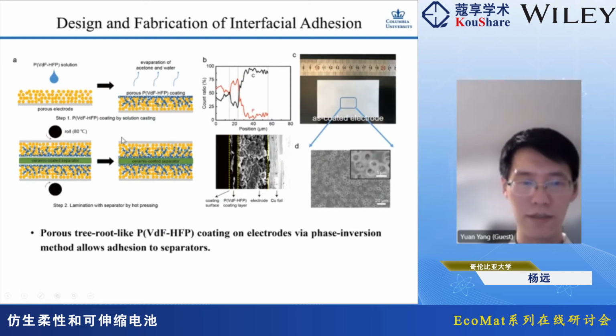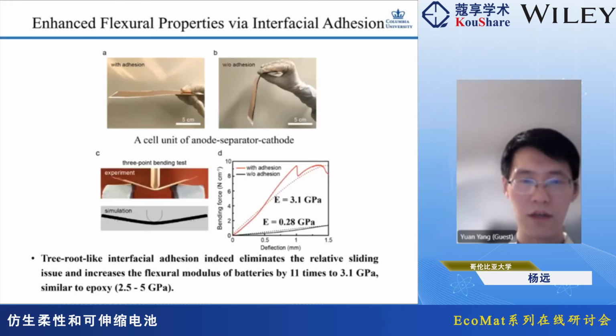Okay, so basically we use this simple solution process to form the tree root-like interfacial adhesion to make the batteries stronger against bending. And from the bending test, we can see with the adhesion, the bending force is actually about 10 times that of a conventional battery, and the modulus is about 3 gigapascal. So that's actually similar to epoxy, and epoxy is a well-known structural polymer. So it means it has a property approaching the structural components.